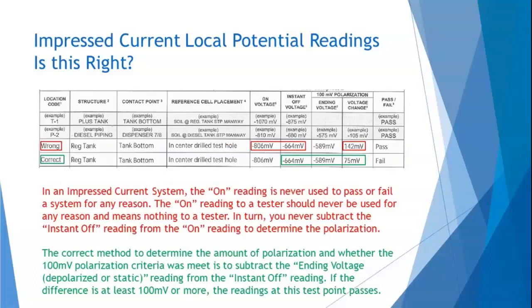Another thing we see out there is in impressed current systems, when we're using the 100 millivolt polarization criteria, some people will use the on reading minus the instant off reading to determine if I met 100 millivolt polarization. As I stated before, the on reading should never be used for any purpose. It is a false number.